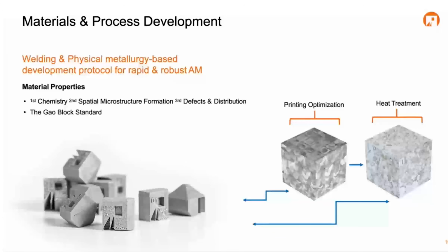Finally, oftentimes you'll see these process maps where the first thing developed is a laser speed versus power curve, where we're optimizing for density. That's really the last thing that we optimize for, because at that point it's really a geometric problem. But if you want the best material properties, you've got to start with the best microstructure that you can get from the manufacturing process.